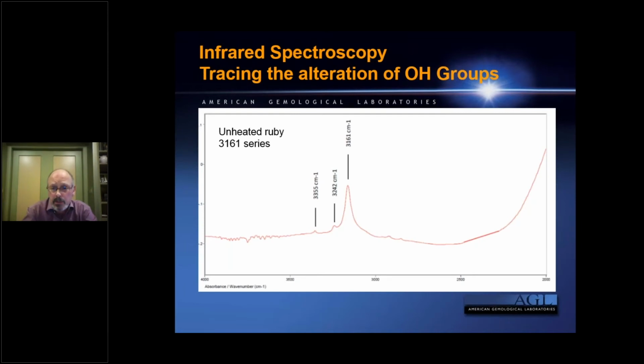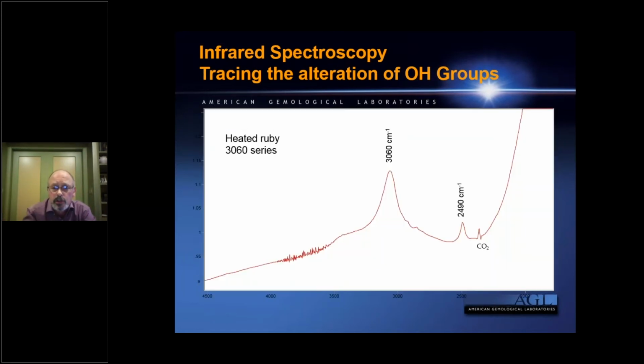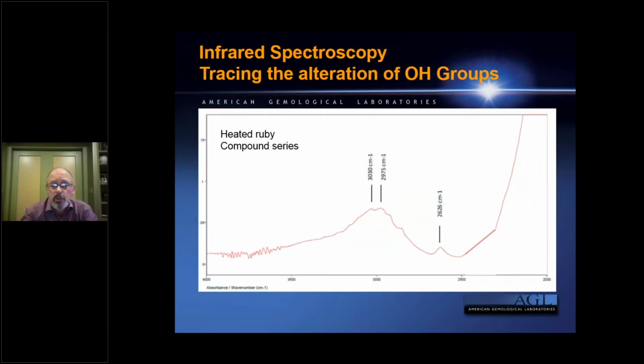You have other bands. I mentioned before this 3161 series. This will be reduced as you elevate temperatures, and they will eventually transition into other structures like a 3060 series. Depending on the heating conditions and the chemistry of the stone, you may get more compound structures. But what is important here is that when you see these kinds of infrared spectra, you have evidence that the stone has been heated, even at relatively lower temperatures. This is an effective tool.